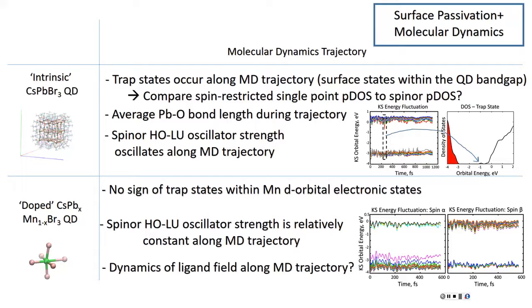I think the energy was 2.4 eV, so green. Actually, no, that'd be more. But this agrees with experimental, just by accident, because we use PBE for the band gap, so it's about half lower than it should be. The PBE functional underestimates by about half.